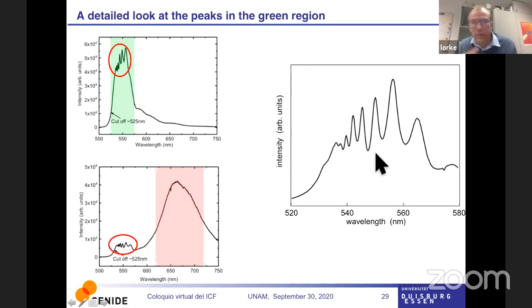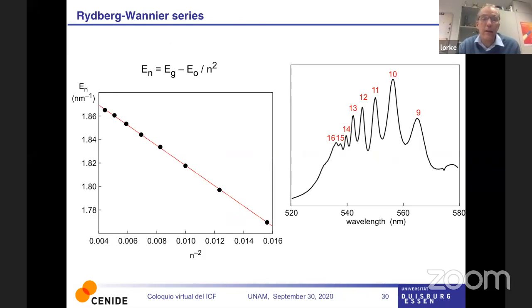We tried to make sense out of this. Of course, we first thought, oh yeah, it's something like resonances, parallel plate, whispering gallery. Nothing fit, but something fit extremely well. That is a formula where you plot the energy of the resonances, or the inverse wavelength, which is proportional, against n to the -2, where n is an integer number. Here, n is 9, 10, 11, 12, 13, 14, 15, and 16. And minus E0 divided by n squared. That's the Rydberg series, and E0 is the Rydberg energy.